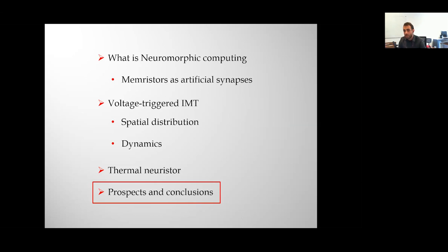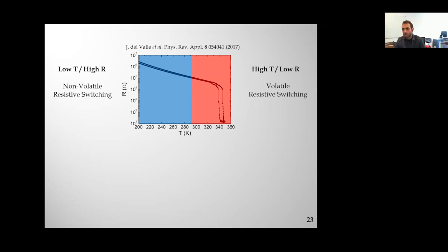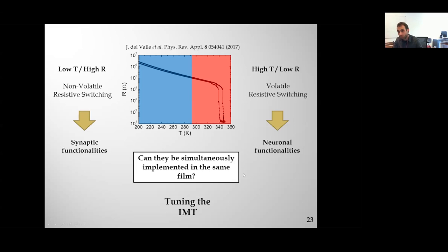So with this, I'm going to move to the prospects. Where to now? One of the things that we observe in this type of material, in vanadium oxides, is that you can observe both types of resistive switching. When you're at low temperature, with high resistance, you can apply a strong electric field and induce the motion of oxygen vacancies, and you observe non-volatile resistive switching. When you're at a higher temperature or lower resistance, closer to this transition, you have volatile resistive switching. That is very interesting because it means that in the same material, you could have both synaptic functionalities and neuronal functionalities.